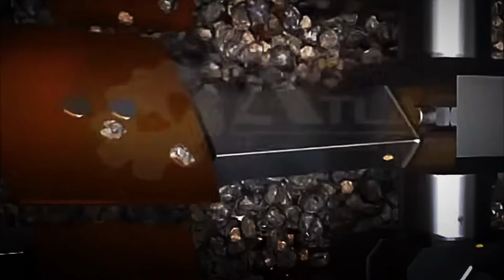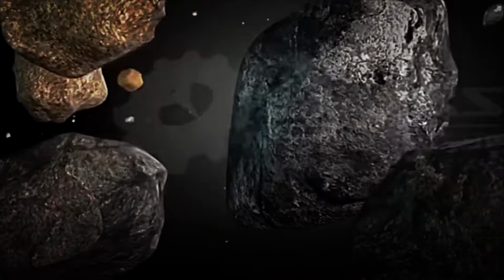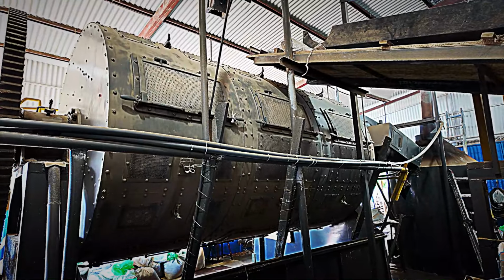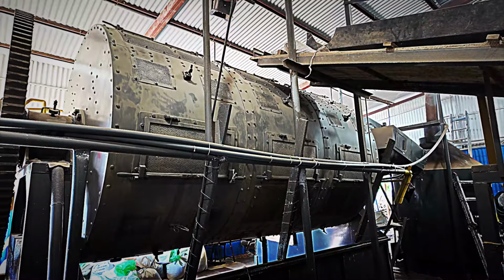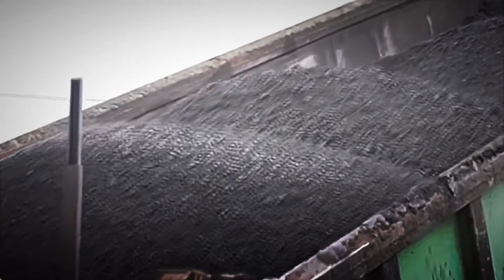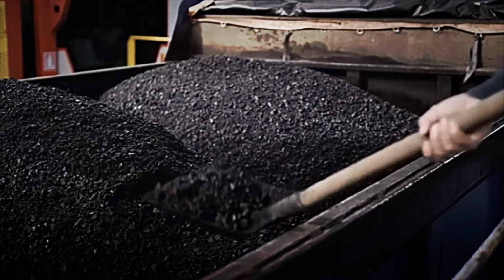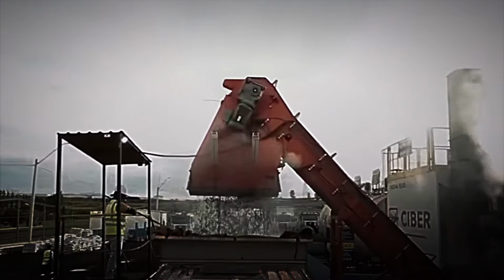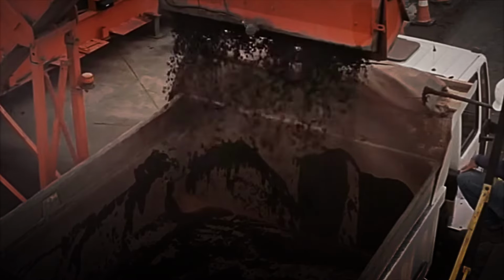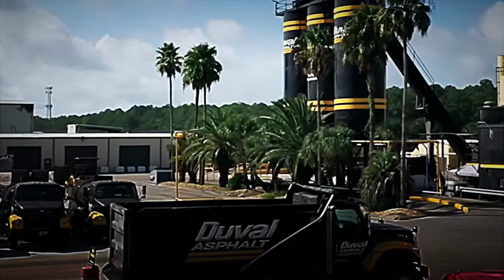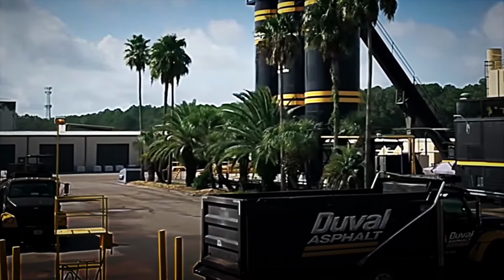The mixture is made inside equipment equipped with paddles designed to withstand high temperatures. These paddles generate a continuous and uniform motion that keeps the bitumen and rubber in contact for a period that usually lasts between 30 and 60 minutes. This stirring time is not random, as it is essential for both materials to interact correctly. During this phase, the rubber does not merely distribute itself within the bitumen, but also absorbs part of its lighter oils and expands in a controlled manner.